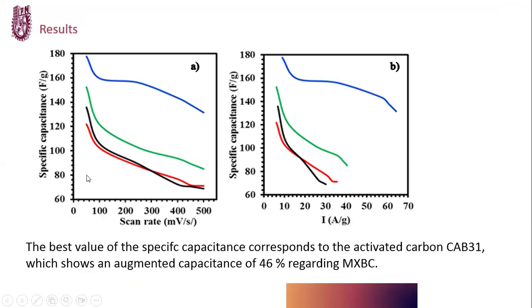In the figure at the left, we observe the specific capacitance values plotted as a function of voltage sweep rate. The high capacitance values at these current density values demonstrate the rapid diffusion of ions in the electrolyte solution. In the figure at the right, we have the values of the specific capacitance as a function of the current density. The best value of specific capacitance corresponds to the activated carbon CAB31, which shows an augmented capacity of 46% regarding bituminous carbon.